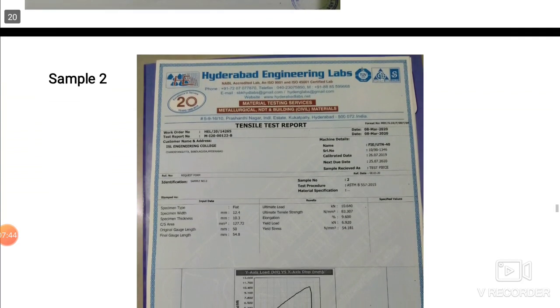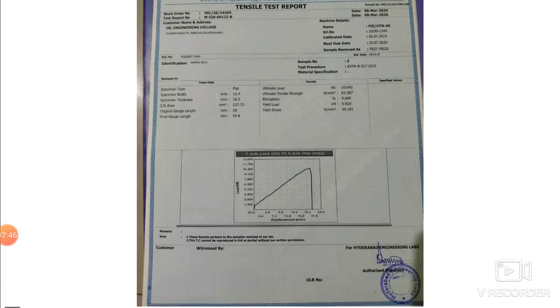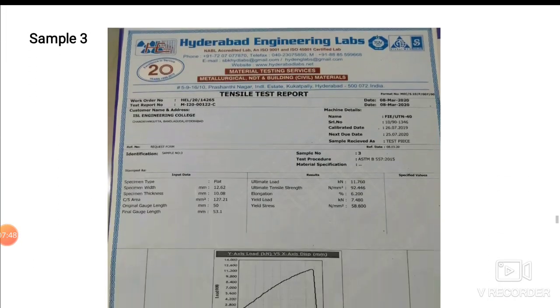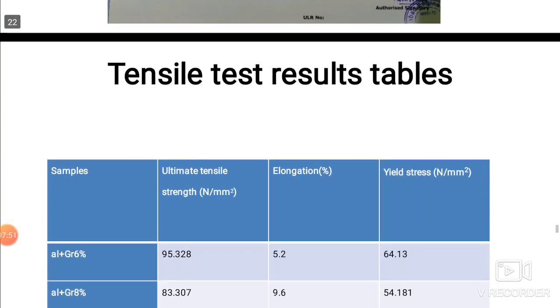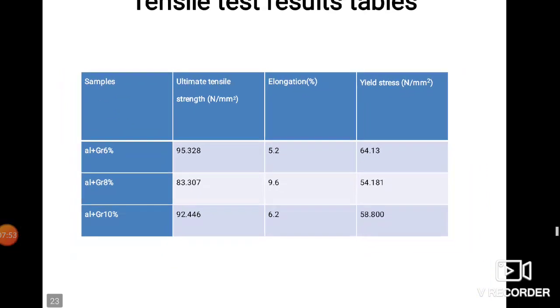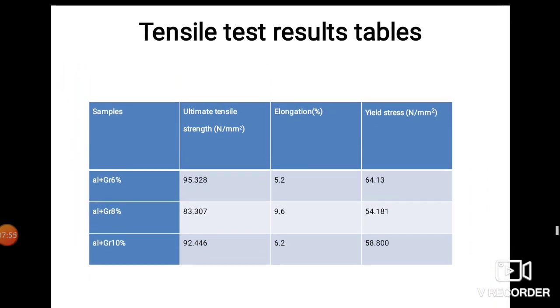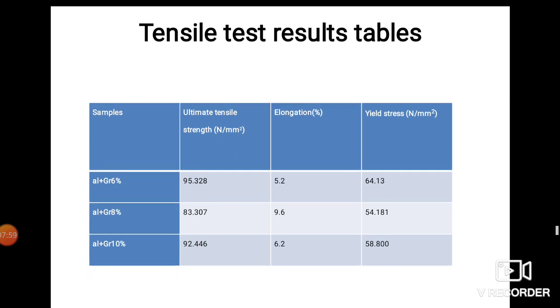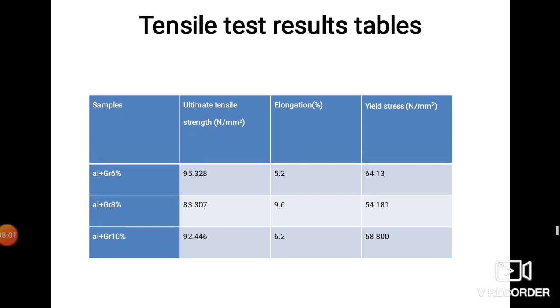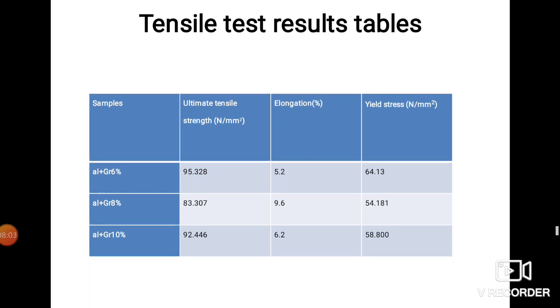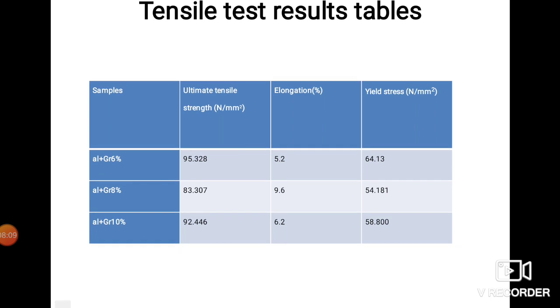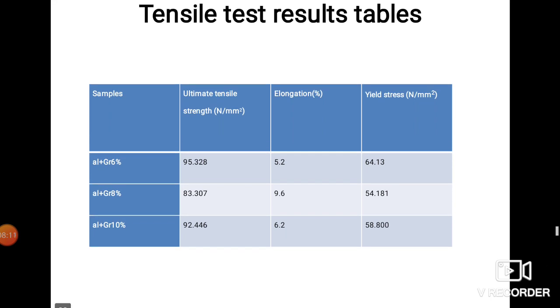Next, we have also completed the test with all the three samples and you can see all those images on the screen. I will explain the samples and the results we have got from it. You can see that with the 6% proportion, we got the ultimate tensile strength of 95.328 Newton per mm square, and the elongation was 5.2%, with a yield strength of 64.13 Newton per mm square.